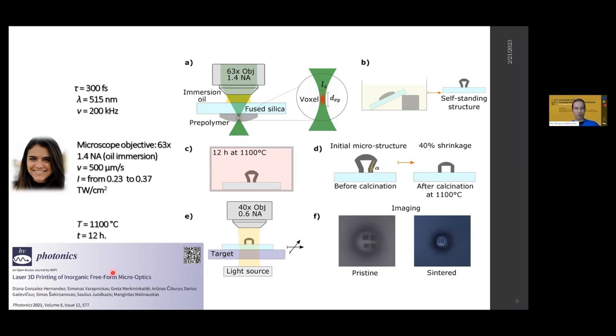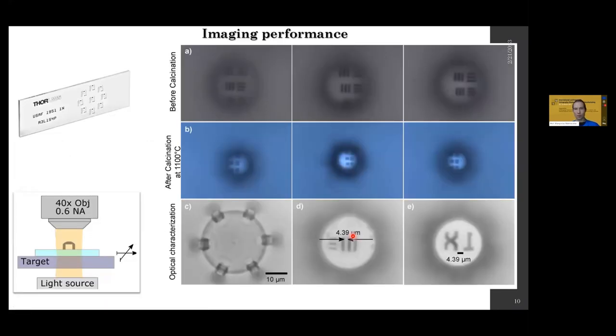We have published this work in the Photonics journal, an open access one. And here are some examples of imaging performance before calcination of three lenses. After calcination, we see that our lens shrinks, but it performs imaging and the resolved features can reach below 5 micrometers for a single element and clearly resolve whatever object we're looking at. In this case, it was a USAF 1951 target or chart structure. So by simply putting it into a laser fabrication setup we could achieve imaging properties characterization.